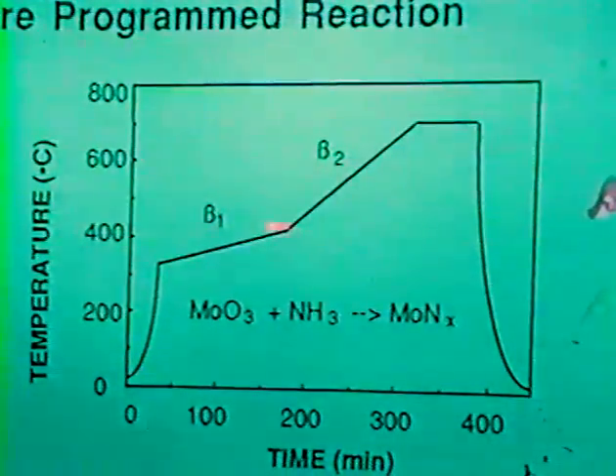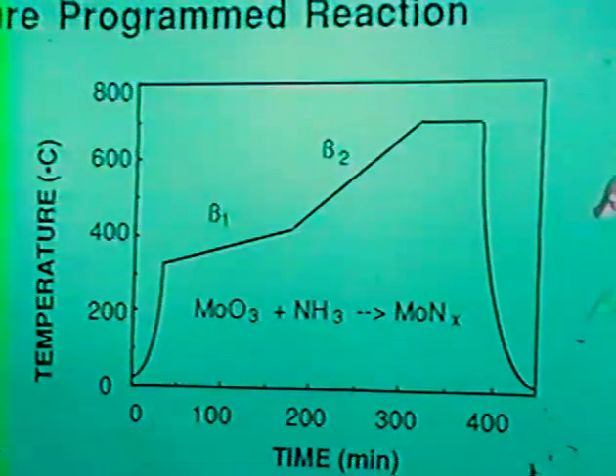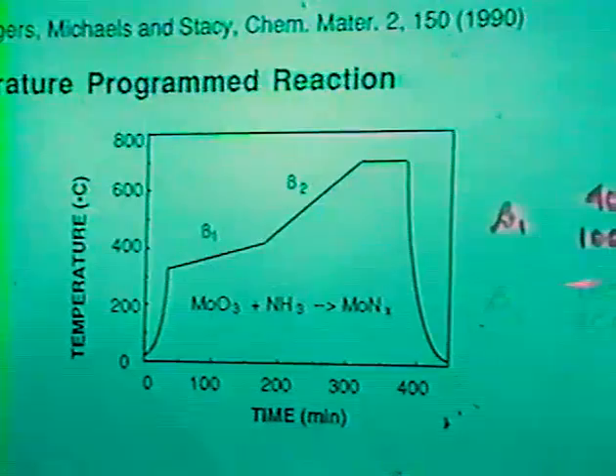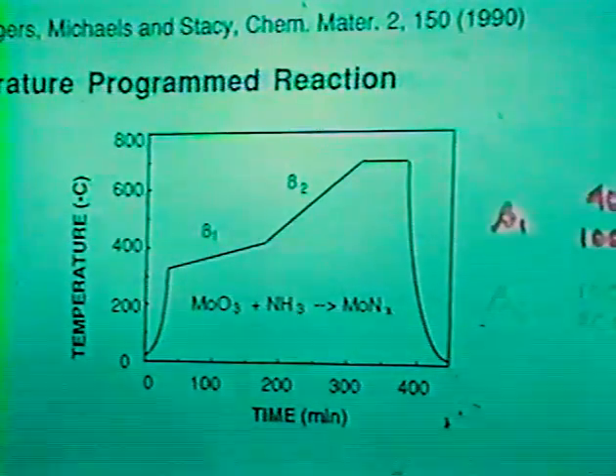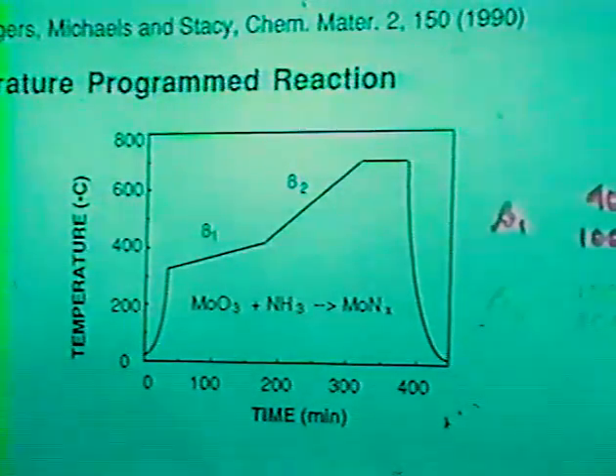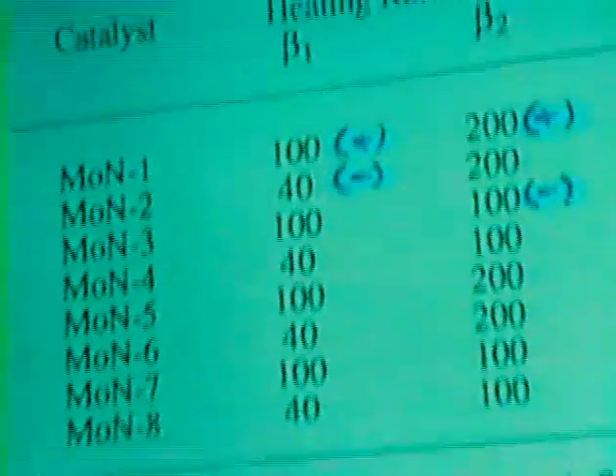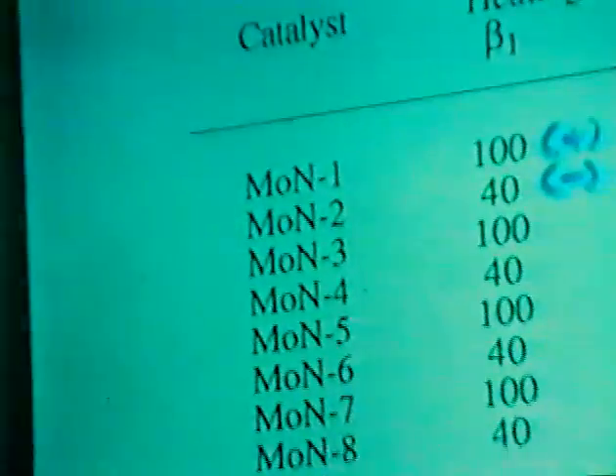Believing that we could control the selectivity and perhaps the structure of the materials by controlling the heating rate, you'll notice that we employed two different heating schedules. We heated from about 350 to 450 using beta 1, in this case beta 1 being either 40 K per hour or 100 K per hour. We've used a second heating interval from about 450 to 700 degrees C, and here we used either 100 K per hour or 200 K per hour. Again, we were trying to control the structure of the materials, and in the worst case, see if there was an influence of the first or second heating rate on the structural properties of the materials that were produced.